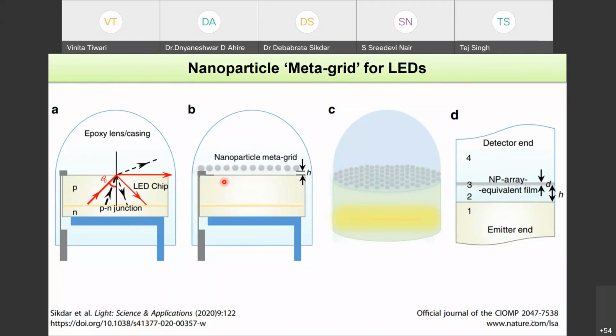Now, what you can do, you can use a nanoparticle metagrid in a very smart manner to effectively cancel out this Fresnel loss. So physically, they will be positioned like this on top of the LED chip, into the casing layer. And this is how they will look. The bottom layer is the emitter layer, and this is the epoxy casing. In between, you will have a nanoparticle array, and you can model it using a nanoparticle array equivalent film.